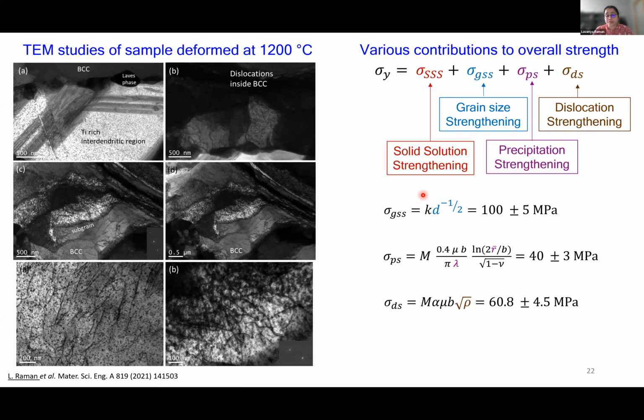So when we try to quantify the individual contributions, we can see that when we add up the grain size, precipitation, and the dislocation strengthening, it comes to only about 200 MPa. Whereas the experimental yield strength at this 1200 degree deformed condition was about 600 MPa. So this clearly shows us that the dominant contribution comes from the solid solution strengthening. Which means for the cast alloy, the solid solution strengthening is what is resulting in the high strength.